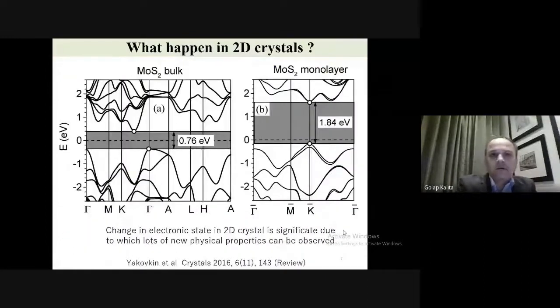And then another interesting aspect in 2D material is this electron dispersion of MoS2 in bulk. So if you see, in case of bulk, it has an indirect band gap. Okay, this is the highest position for valence band and conduction band. If you see, it's an indirect band gap, which is around 0.76 electron volt.